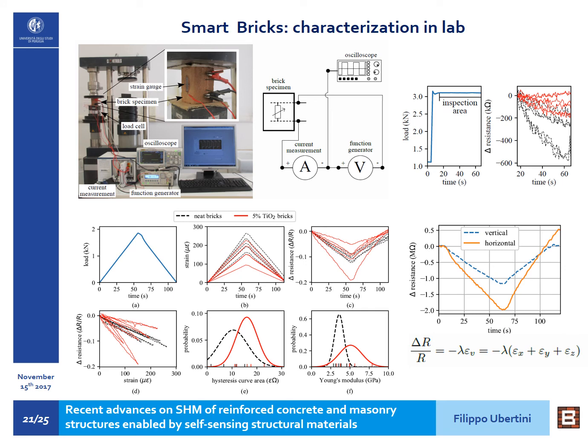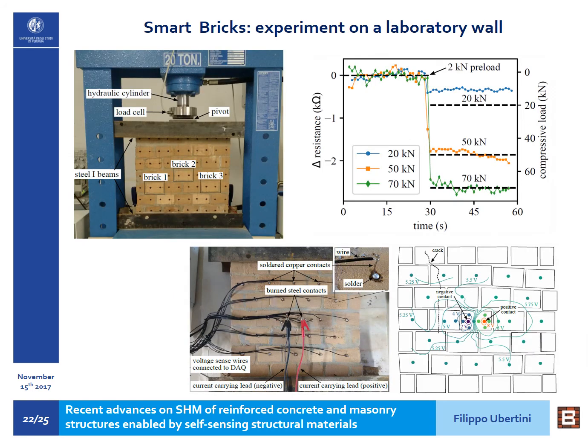This model is now being validated through a micromechanics approach, which I will not show you here, but is suitable for first level investigations. So here you see a demonstration application of the smart brick idea. You have a small masonry wall with 3 smart bricks. This wall is placed in an axial compression machine, and you clearly see on the top right of the slide that if we apply a vertical load to this wall, we have a change in the electrical resistance of the smart bricks that more or less tracks the intensity of the loads.